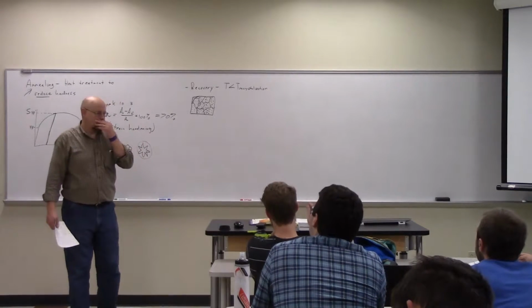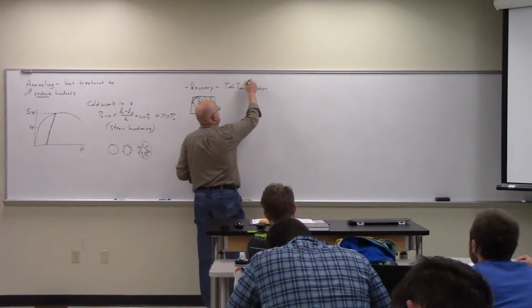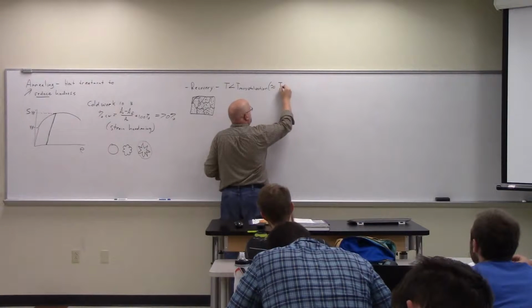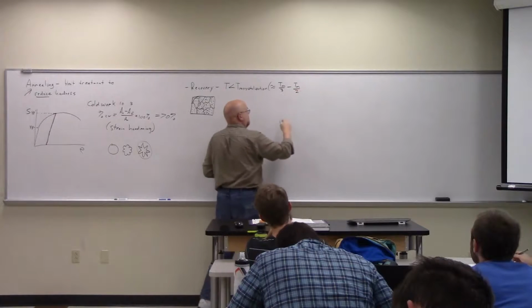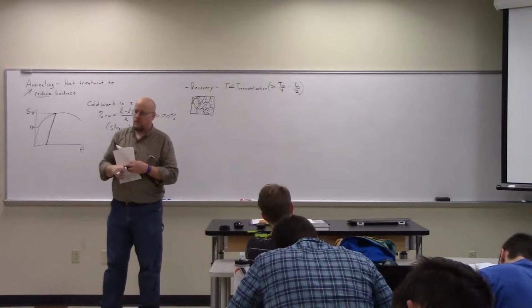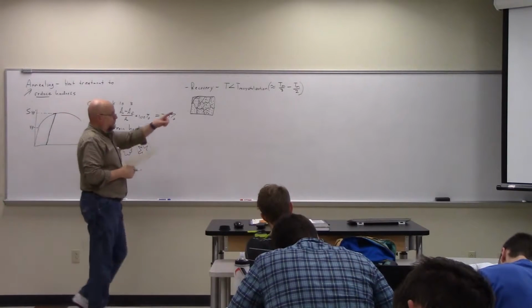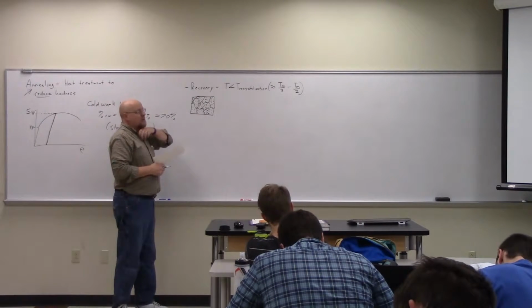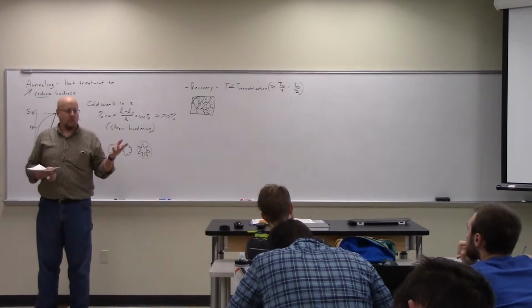Yes? And this is, we're just heating, right? We're just heating it to a temperature less than the recrystallization temperature, which is going to be on the order of 1/3 to 1/2 the melting temperature. Typically, it's just a ballpark kind of number. Okay. As long as you're using an absolute temperature scale. So it just sort of fixes the lattice. So it just allows the lattice to fix itself by atomic diffusion.